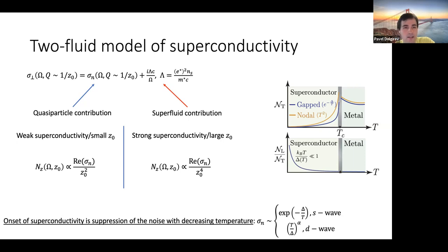Another really exciting point to me is that, as I said before, if you take normal metal, then you can completely ignore longitudinal fluctuations. However, because superconductor opens a gap for quasi-particles, it actually suppresses transverse fluctuations, and the longitudinal can start to dominate. And in reality, at very low temperatures, the actual signal will be entirely dominated by longitudinal noise.